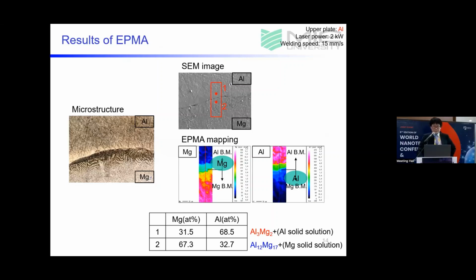EPMA analysis was performed to understand the composition of the interfacial structure. As an example, the results are shown for the condition of the upper plate of Al, a laser power of 2 kilowatts, and a welding speed of 15 millimeters per second. EPMA mapping analysis was performed on the area surrounded by the red square in the same image.